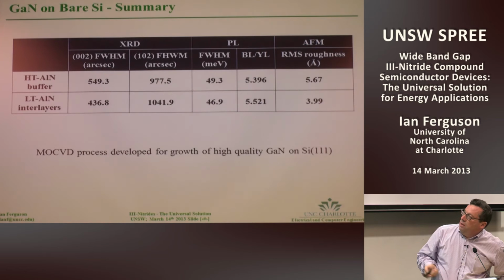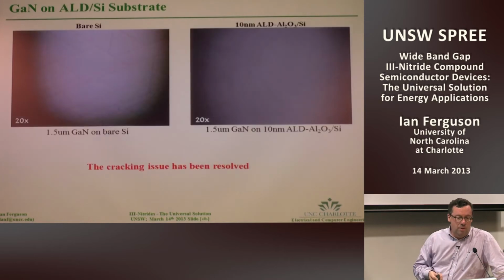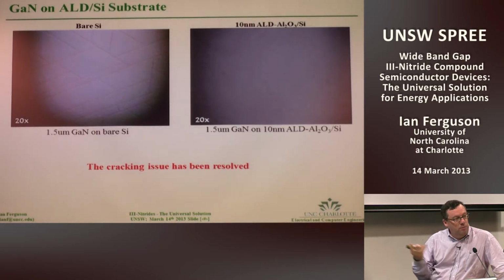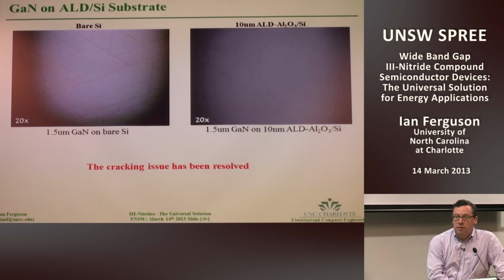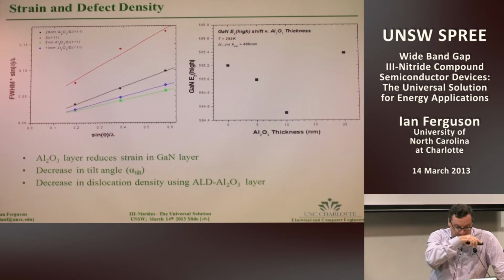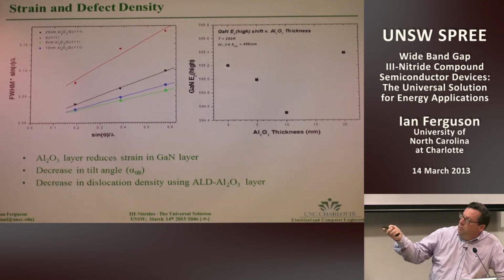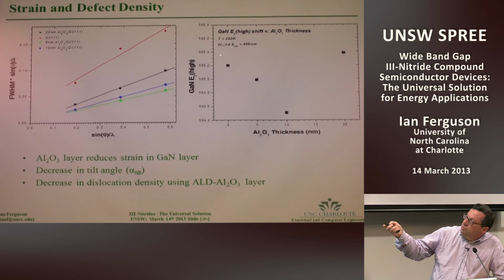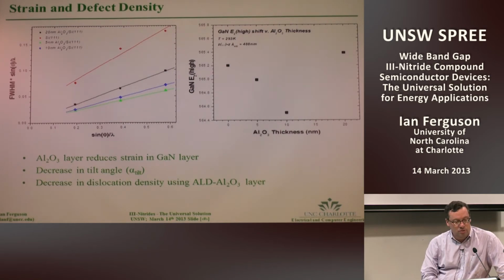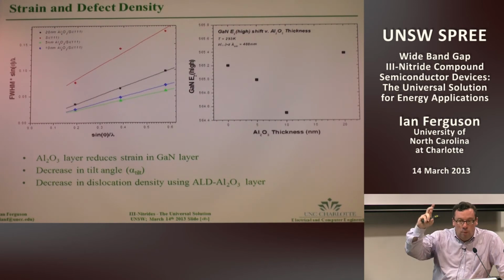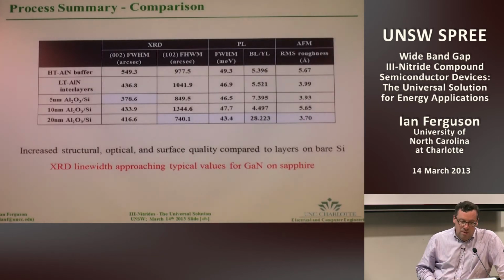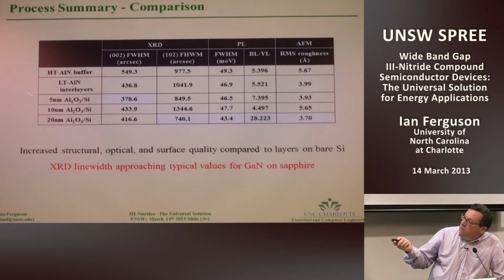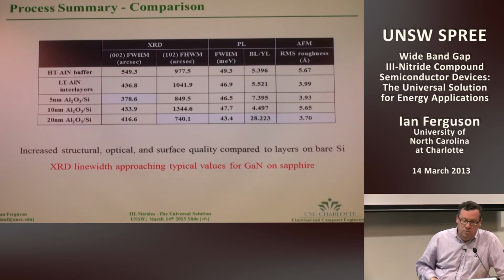So our process was to develop high quality GaN on silicon. This was for comparison. But you see the issue with the silicon was that, because of the thermal mismatch, the materials would crack. When we started doing these intermediate layers, they tended to improve. You would tend to see an optimum aluminum oxide thickness. This is Raman spectroscopy that told you where the material was actually starting to look somewhat better. So there was an optimum thickness for these. But you can see here, we can actually get the material down to something that was somewhat reasonable, like this 20 nanometer, the off-axis reflection was going down.